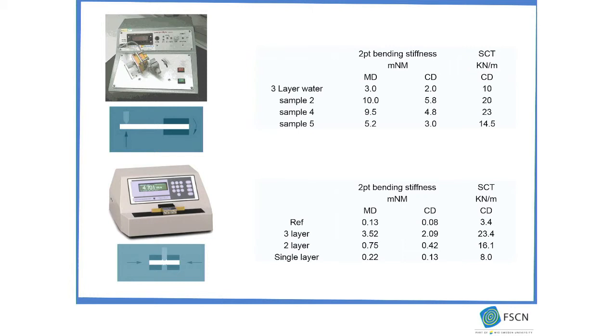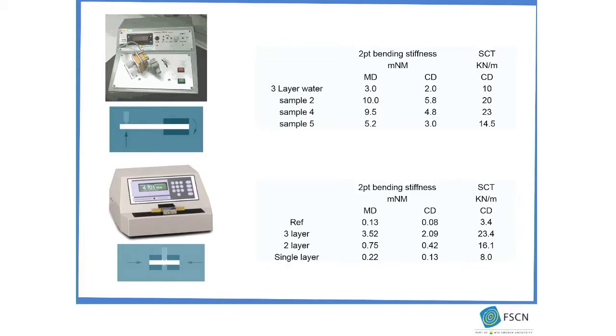And this is the data from the first method: the spray, wash out, and hot press. As you can see, the reference uses water. The bending stiffness is 3 and 2 for the machine direction and the cross direction, and these are the treated materials. You can see most of those are double or triple the result. So we can provide some tough materials.